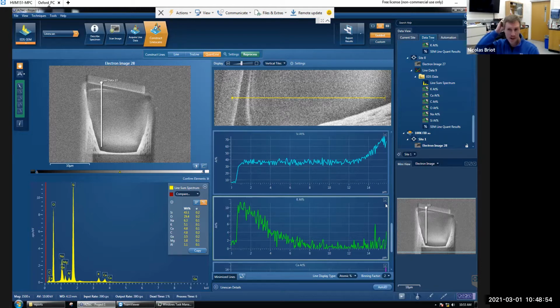We don't have time to make another cross section, but as I was saying earlier, the ball's in your hand. If you want to tell me what you want me to do, if you want me to do another sample, whether it's FIB cross section, XPS, or the EDS line scan on the mechanically prepared samples, you tell me. I know you are doing some mechanical testing on those samples, right? If you're trying to relate what we see in EDS to those mechanical results, feel free to send me an email, and I can look at a couple of samples for you.